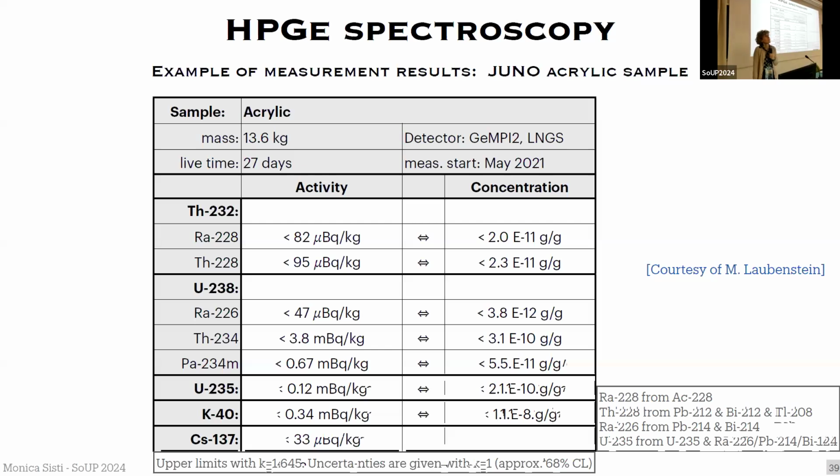I was wondering if there's any background coming from a metal surface or something. Metal, yes, the truss is of metal, but this is much less important. The acrylic vessel is held by columns that are attached to the acrylic, and the cobalt-60 in these columns could be a problem. That's why this stainless steel is of higher quality, with lower radioactivity content with respect to the complete truss.